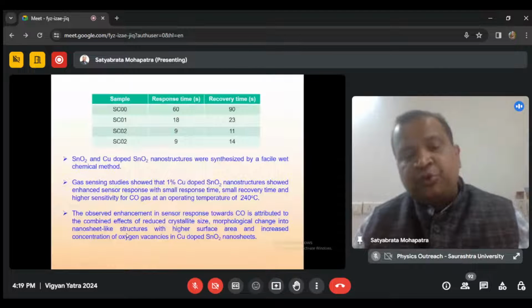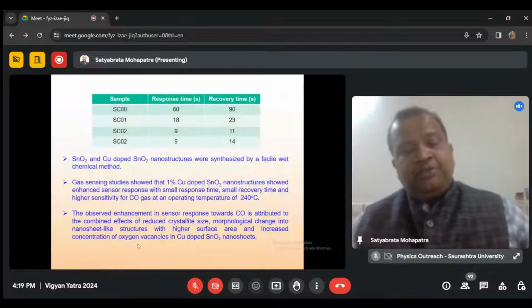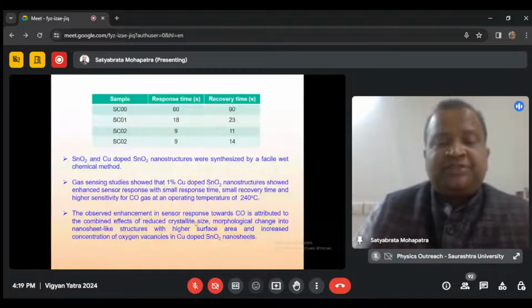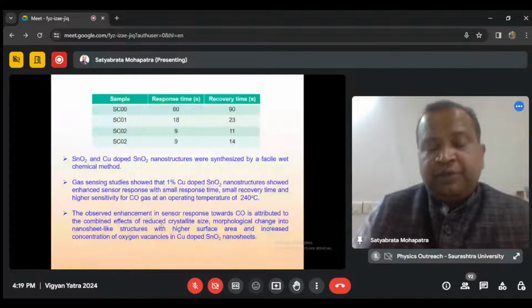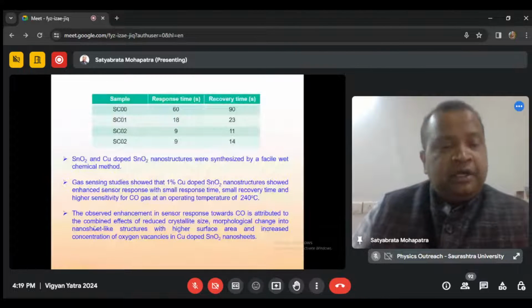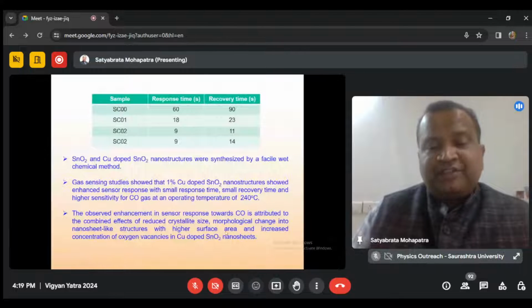And in this case, what we achieved is that the enhanced carbon monoxide sensor response is basically a combined effect of reduced crystallite size, a nanosheet-like morphology with high surface area, and increased concentration of oxygen vacancies.